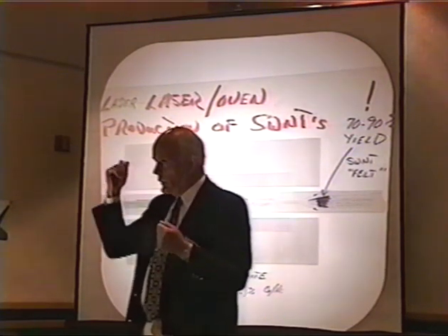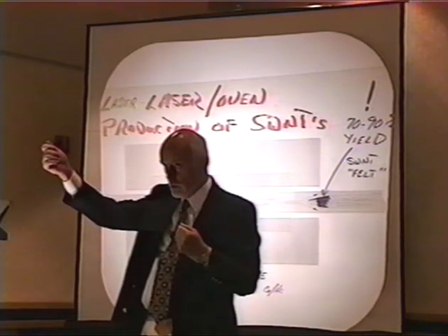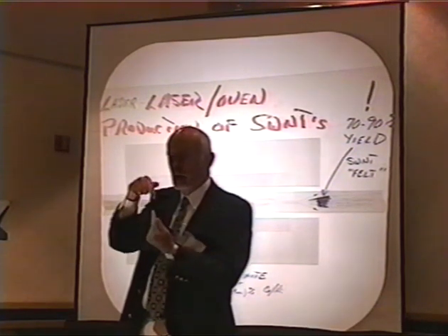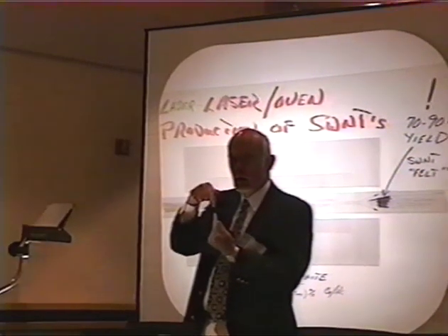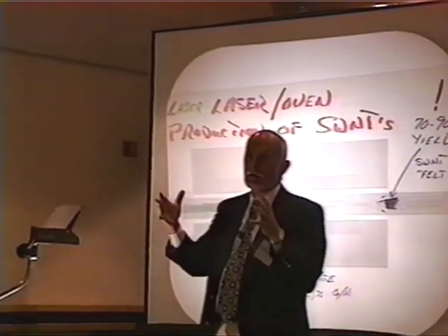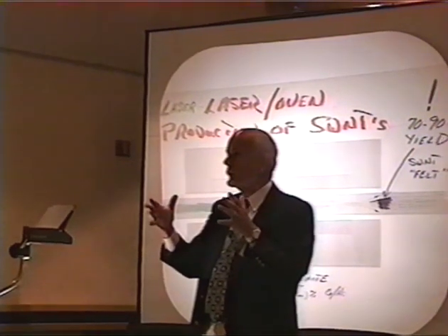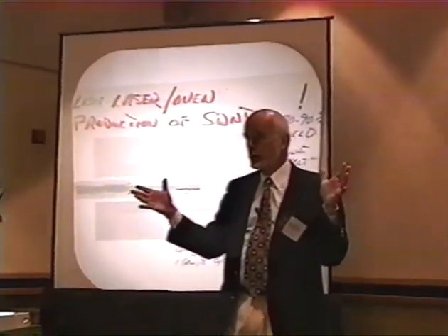In Dr. Iijima's work, it was done by arcing two carbon electrodes together in a methane atmosphere, an inert atmosphere that had about, what, 10 torr methane, was it? 50 torr or something like that? 1,200 torr? 500 torr. With a little bit of iron particles in the anode. And in the IBM Bethune work, it was carbon electrodes with cobalt in the anode in an inert environment. And both of them saw these single-wall nanotubes in small amounts.